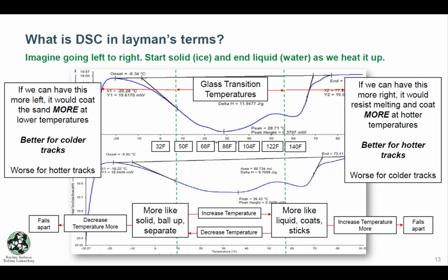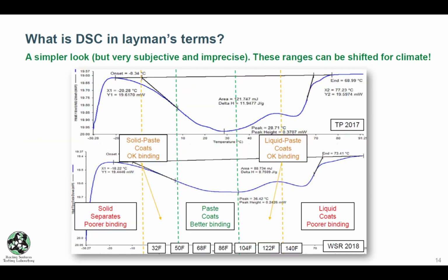It was mentioned earlier that around 0 degrees Celsius, or getting around freezing, we can start seeing the material separate out, and as you continue to decrease the temperature, the material tends to fall apart. But we see the same being true as you increase the temperature. We start losing some of the binding ability of this wax. So this is perhaps a very simplistic way of looking at the DSC data and what it could potentially mean when you're doing a wax selection. And so here I have two lines dropped in green. This is where the wax is really going to act like a paste.